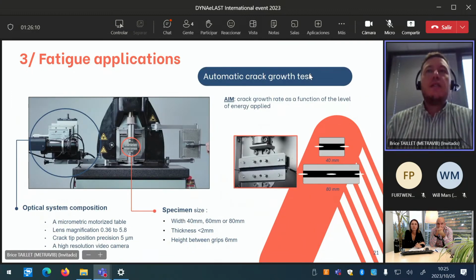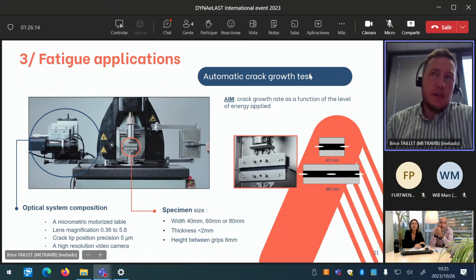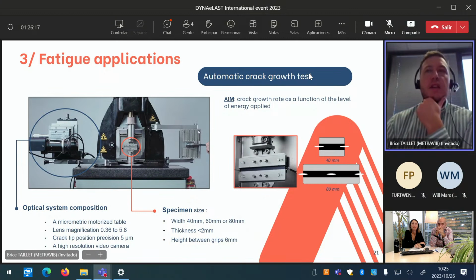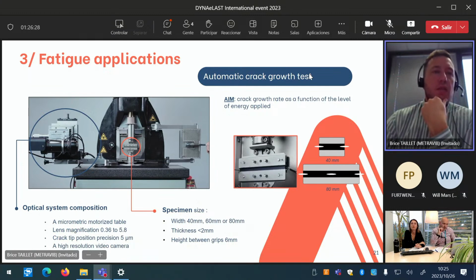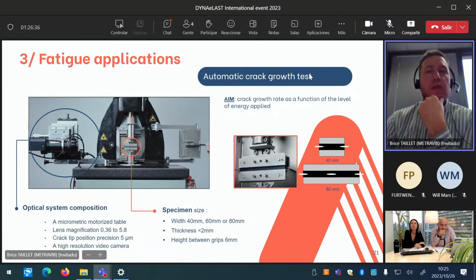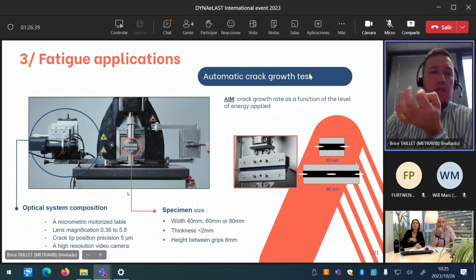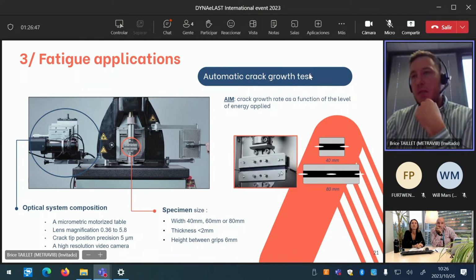One other application is the crack growth test and the automatic crack growth test. And the aim of this test is to get the crack growth rate as a function of the level of energy applied. Okay. The composition is quite basic. We use an optical system with a micrometric motorized table with a lens magnification, and we are able with this to characterize a crack tip position with a precision of 5 micrometers. We use for this a high resolution video camera, and we are able to work with this kind of specimen, 2 dimensions available, 40 millimeters and 80 millimeters. And with the larger specimen, we are able to follow 4 cracks at the same time.